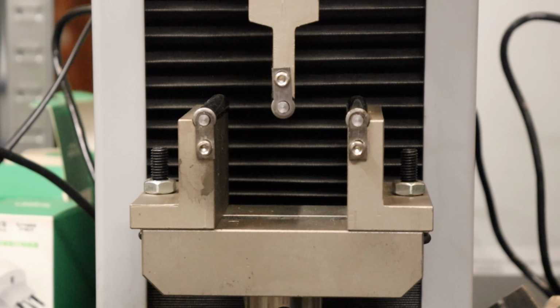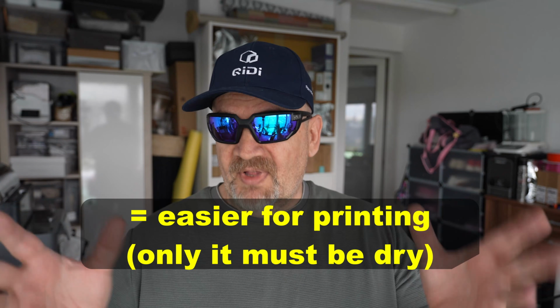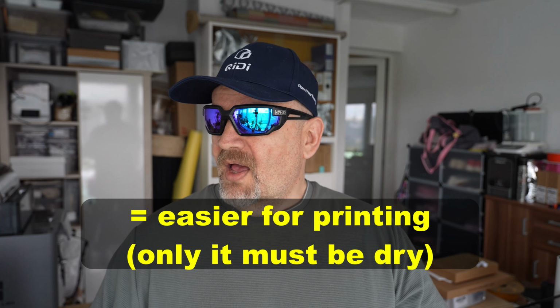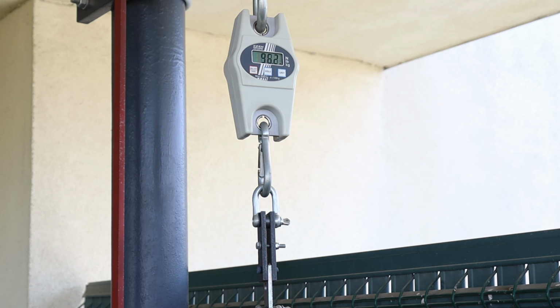About this ASA-CF, theoretically it should be stiffer, but this is one of the weakest fiber reinforced ASA materials I ever tested. Two advantages I can see: it's a little bit stiffer, for example, it resists a little bit better to bending, and it will increase a little bit that temperature resistance. Of course, the dimensional accuracy, maybe that is very important for some users, but otherwise, for example, on that shear test printed in horizontal position, fibers always help here, but this strength was very similar like regular ASA. These fibers are quite weak according to my experience.